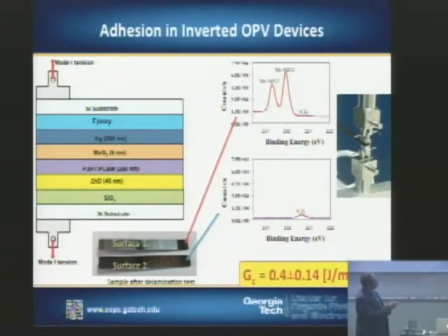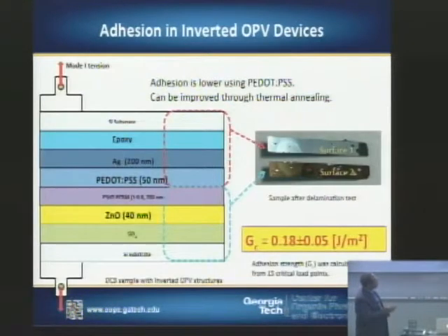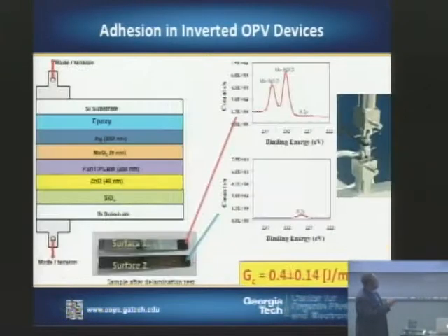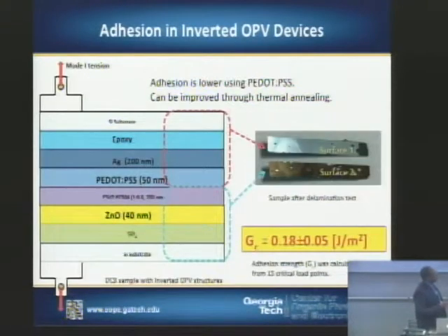If we change this to a polymer contact, so if we go to PEDOT:PSS, what we will see is that, let me just back up. The strain energy release rate here is about 0.4 joules per meter squared. If we go to PEDOT:PSS, we'll actually see this value drop. So there's a detriment to going to some of these polymer films if you don't process them correctly. One of the things we have seen in our work is that, yes, there is hope. You can do annealing of these interfaces, and they will increase in strength. You can also do some other pre-processing. This is still an area of active research, to understand how to improve this interface without damaging the overall performance of the organic photovoltaic.